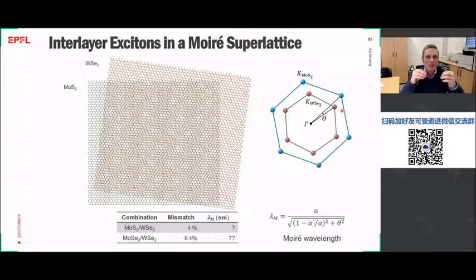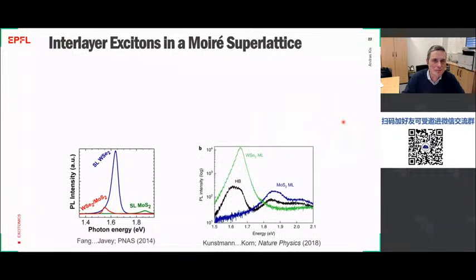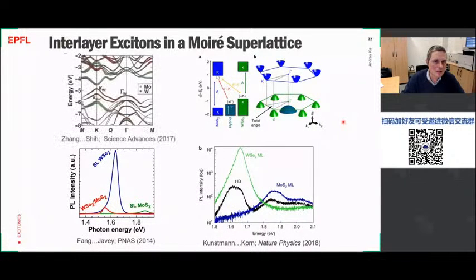because there is no way to actually put them in the same place in K space. So to recombine a hole in tungsten diselenide or an electron in tungsten diselenide with the opposite charge in MoS2, you would actually have to change a little bit the momentum of the charge carriers. And this then explains why the interlayer excitons occur at the energy at which they occur.